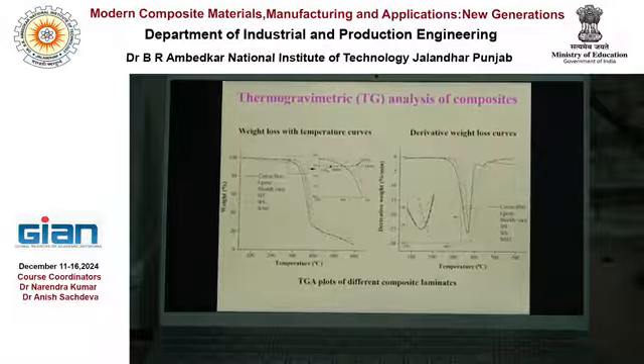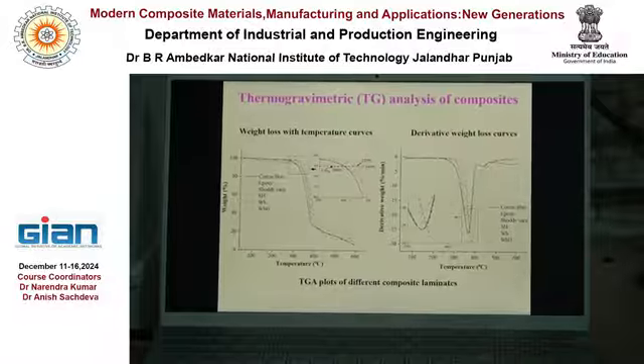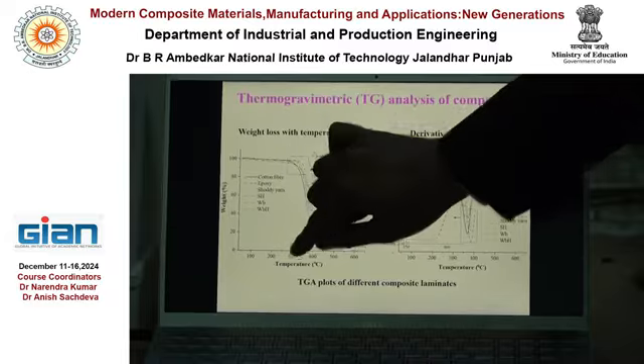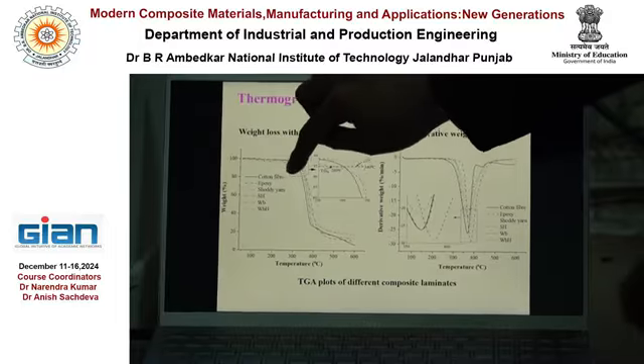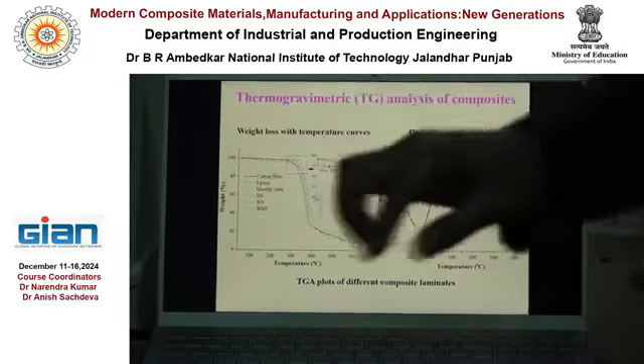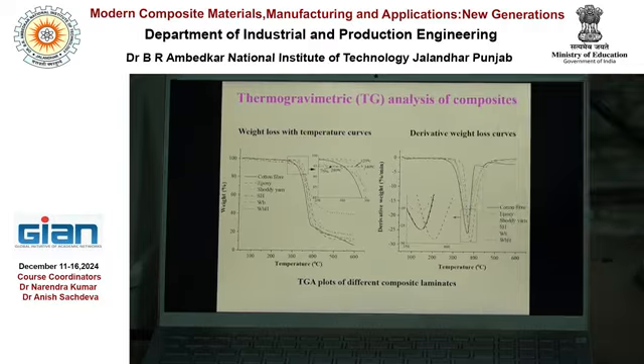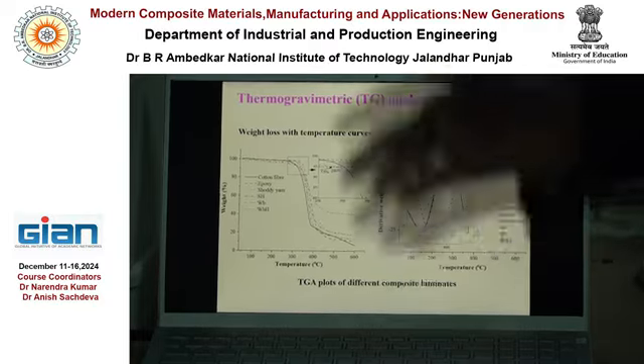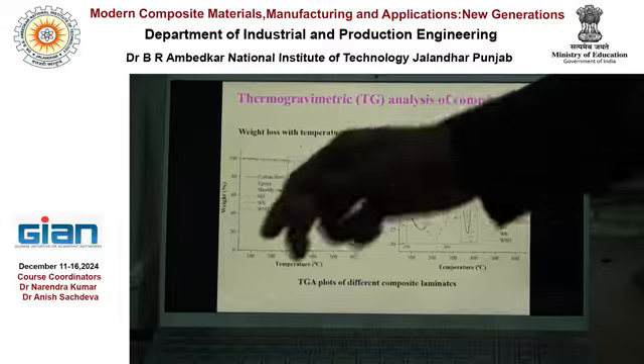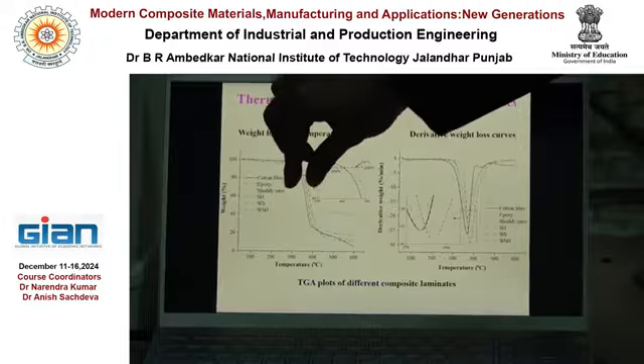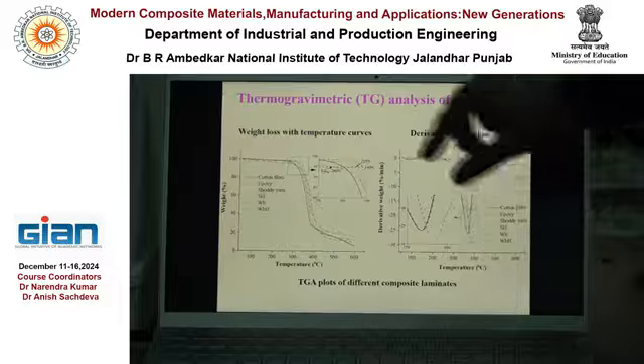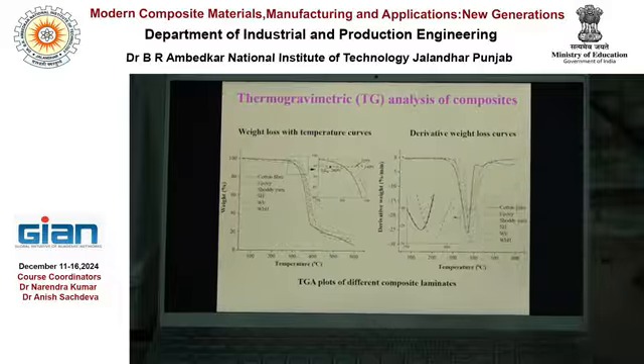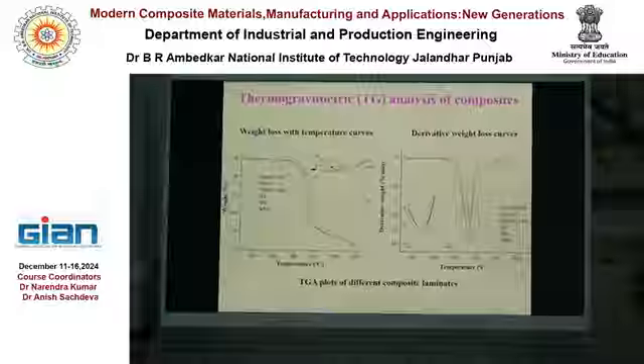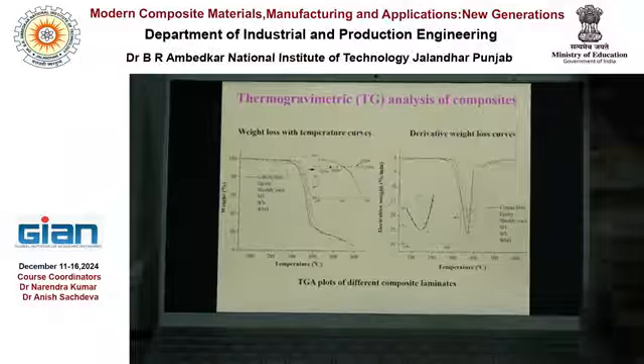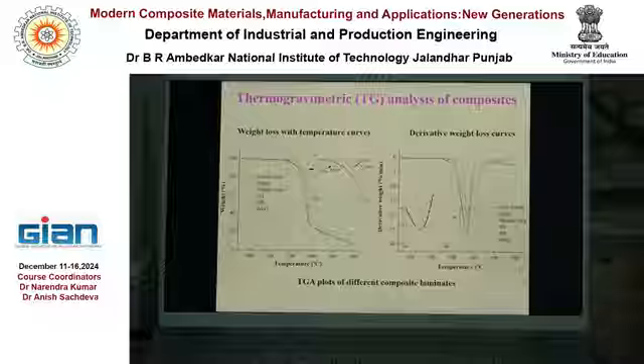Major weight loss happens from 300 degrees centigrade to 400 degrees. Major decomposition of that material. Yes, sir. So this is the onset temperature. Onset temperature means the temperature from where the sudden change in the weight of the material actually takes place. And we also measure the 5% weight loss temperature, that is, at how much temperature there is a 5% weight loss.